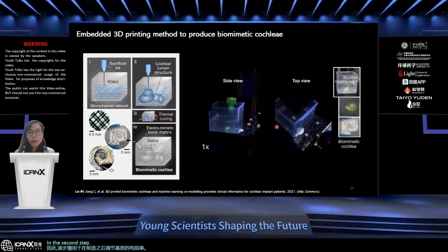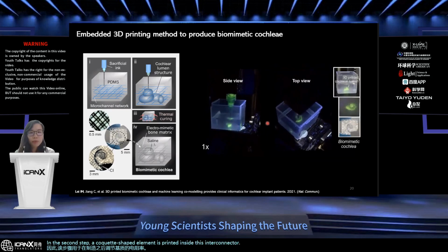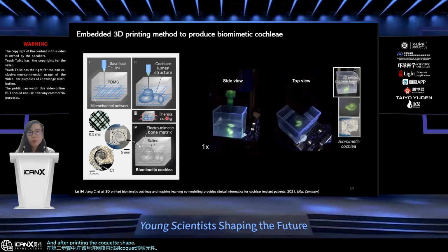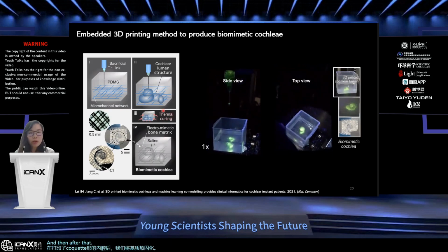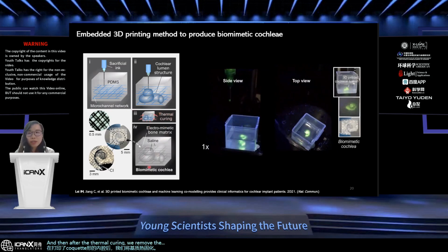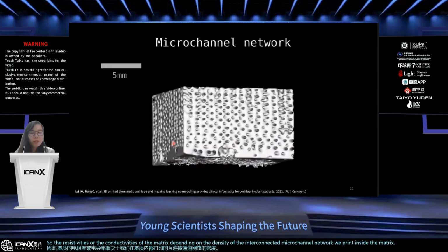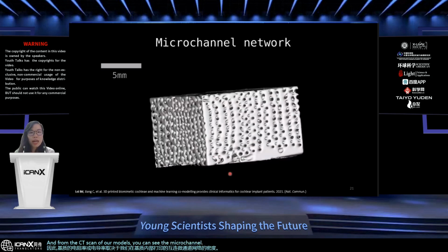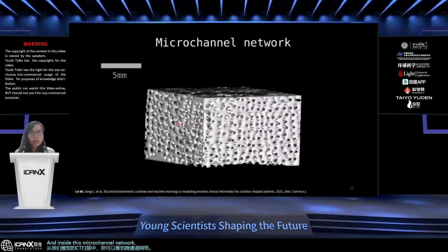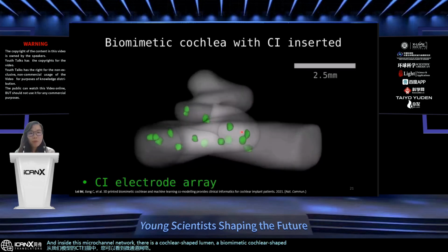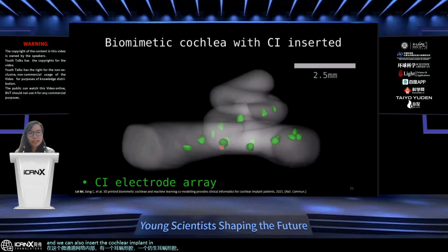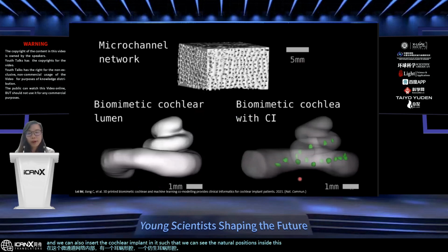In the second step, a cochlear-shaped lumen is printed inside this interconnected network. After printing the cochlear-shaped lumen, we thermally cure the matrix. After the thermal curing, we remove the sacrificial material and fill the microchannel network with saline such that the matrix becomes conductive. The resistivity or conductivity of the matrix depends on the density of the interconnected microchannel network we print inside the matrix. From the CT scan of our models, you can see the microchannel network, and inside it there is a biomimetic cochlear-shaped lumen. We can also insert the cochlear implant in it such that we can see the electrode positions inside this biomimetic cochlea.